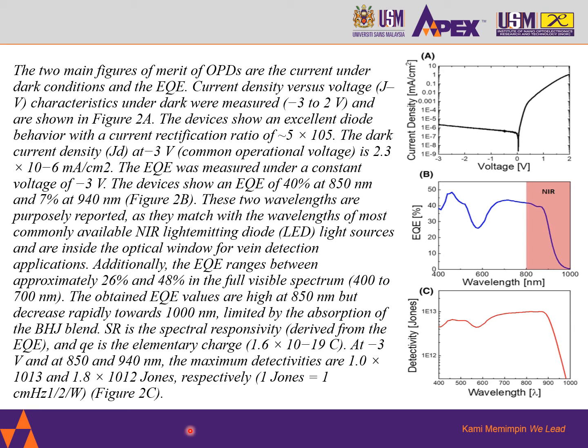The two main figures of merit of organic photodiodes are current under dark conditions and the EQE. Current density versus voltage, J versus V characteristics under dark were measured and are shown in figure 2a. The devices show an excellent diode behavior with a rectification ratio of 5 x 10^5. The dark current density, JD, at 3 volt, a common operational voltage, is 2.3 x 10^-6 milliampere per centimeter square.